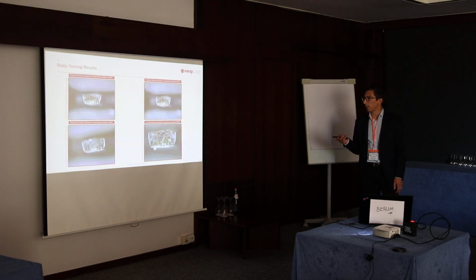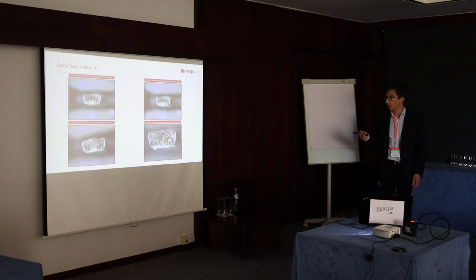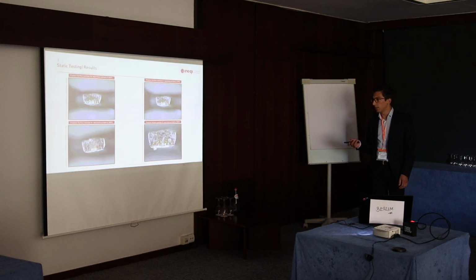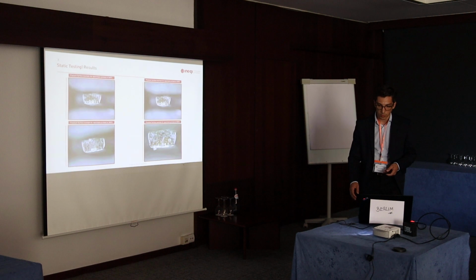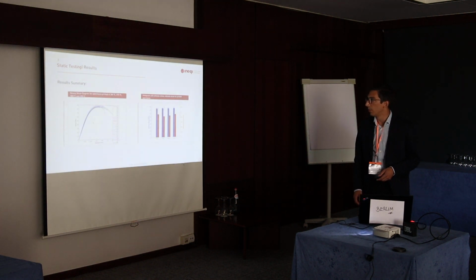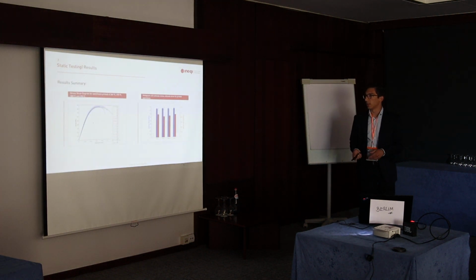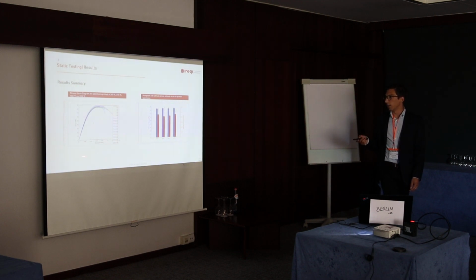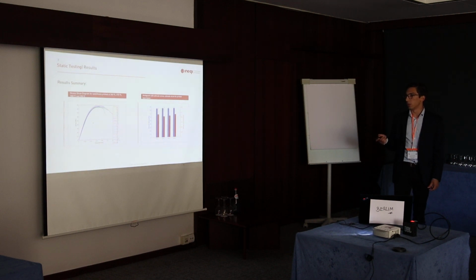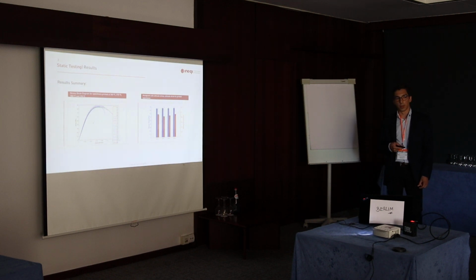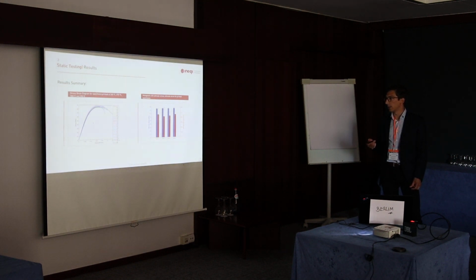This is again the surface fractures for 360, 370, 380 and 390. These are examples for each of the temperatures. So in comparison, to try and make some sense of these tensile results, we have a little bit of this dispersion here, but in general we can say that we have a max stress of around 85 to 90, which is a little bit below the manufacturer specification, which we believe to be in accordance to what was expected. And we also have a big variance in ultimate strain.